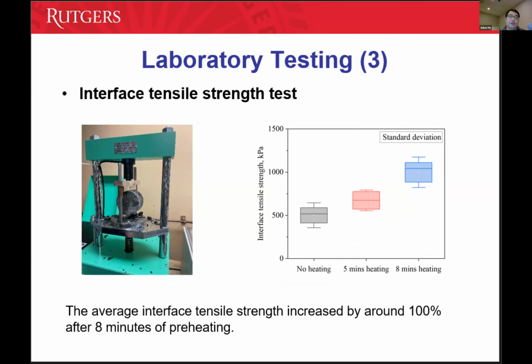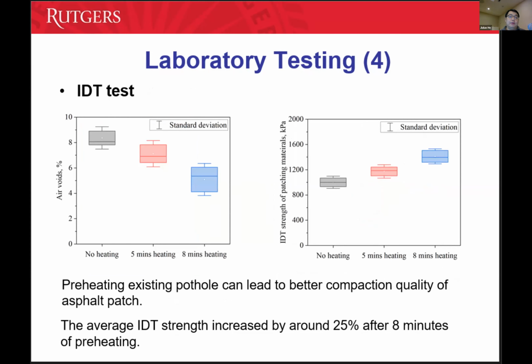And similarly, for the interface tensile, this is at the edge interface. We're able to get the cores even without a heating case, but the strength is about 500 kilopascal. And then with a few minutes of heating, you can see how the interface tensile strength increases, almost doubled after 8 minutes. This is for the patch material itself in indirect tensile testing. So in this case, you can see how this IDT strength is increased.